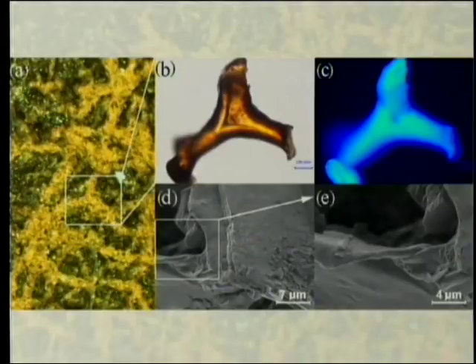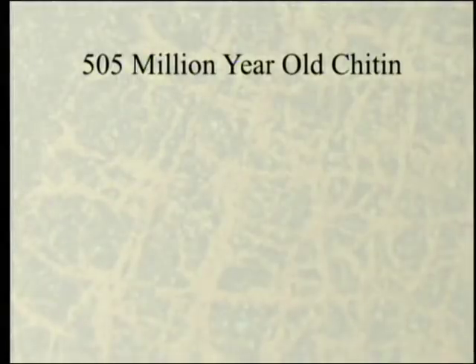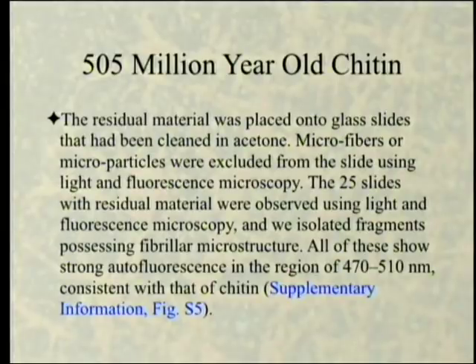And here's the figure 3, and you can see one of the spicules that they've broken off from this area, and you can see that it lights up very nicely with that calcofluor white. And here's a little bit of what it looks like under the scanning electron microscope, and you can see it has a structure that doesn't look like it came from any geologic process. Looks like it's original material. The residual material was placed on glass slides that had been cleaned in acetone. Microfibers or microparticles were excluded from the slide using light and fluorescent microscopy. See something that doesn't look like what we're looking for, we take it out.